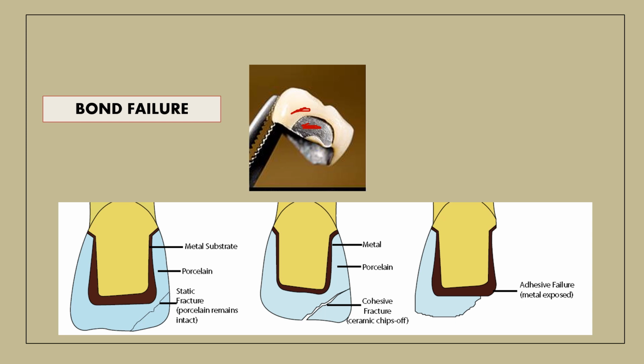So going in detail into the bond failure, this bond failure is of three types, that is your static fracture, cohesive fracture and adhesive failure. This static fracture and cohesive fracture occur in the ceramic itself, where in the static fracture the porcelain remains intact, whereas in the cohesive fracture you will see something called your ceramic chipping off. Whereas this adhesive failure occurs at the metal ceramic interface, resulting in the exposure of the metal.